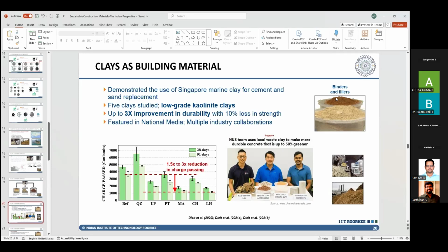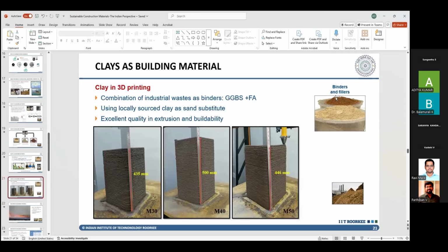Okay, and so much so that we got featured in the local news channel also for our work. Right. In IIT Roorkee, I'm using clay without heating for generating printable mixes, low carbon printable mixes, and we have been able to achieve very good performance based on clay concrete, because clay can act as a natural viscosity modifier and can help improve two things: extrudability, that is the ability of concrete to come out of the printing nozzle, and buildability, that is the ability of concrete to stack up in layers without collapsing.